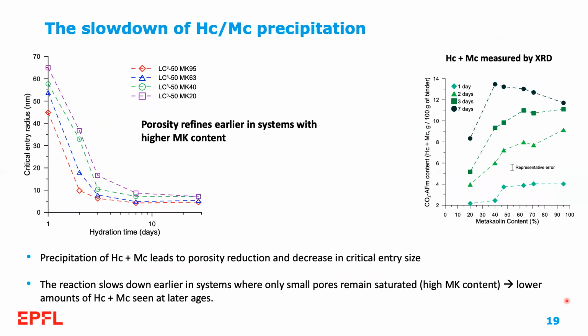We do observe a slowdown in the formation of carboaluminates over time. And it's very curious that this slowdown occurs first in systems with higher metakaolin content and occurs later in systems with lower metakaolin content, as we see here in the plot. In the beginning, the higher the amount of metakaolin in my LC3, the higher the amount of hemi and monocarboaluminate that I form. But as early as 7 days, we have a reversal of this trend, and we observe lower amounts of carboaluminates in the higher grade systems, and the higher amounts are actually observed in the medium grade ones.